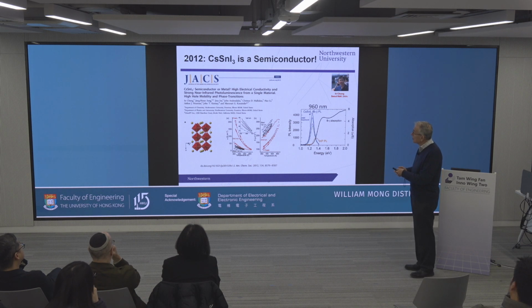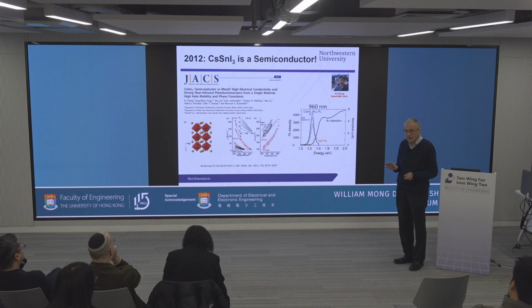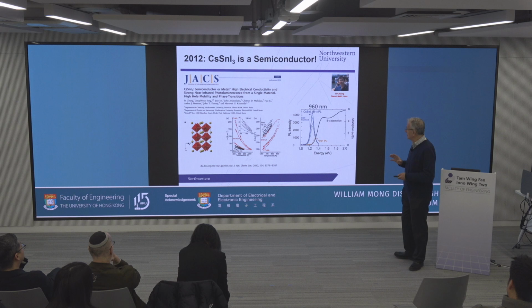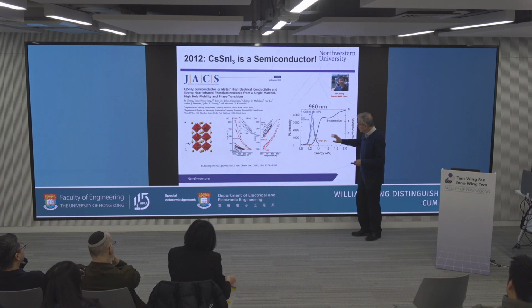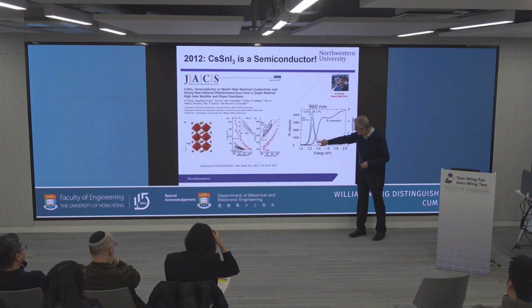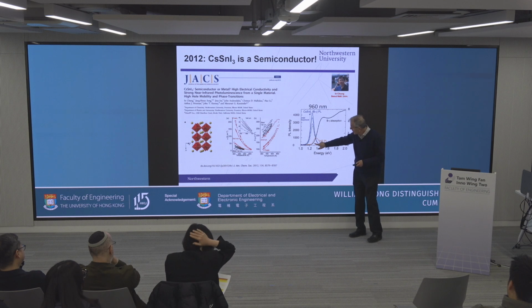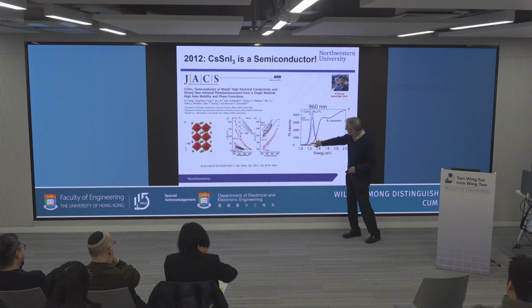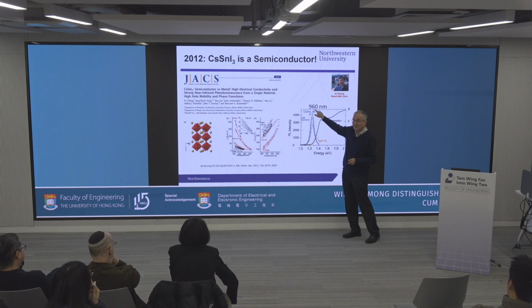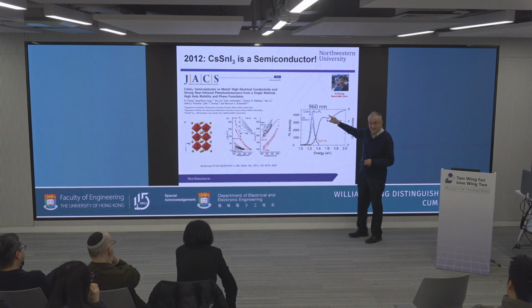Eventually, we started in 2008. The paper came out in 2012. And indeed, this material is not a metal. It's a semiconductor. We made it pure, high quality. Here's the absorption spectrum. You see, the band gap is 1.3. And then look at the emission. Band gap emission at 960, perfect. That's what we need. And it's actually room temperature and intense.